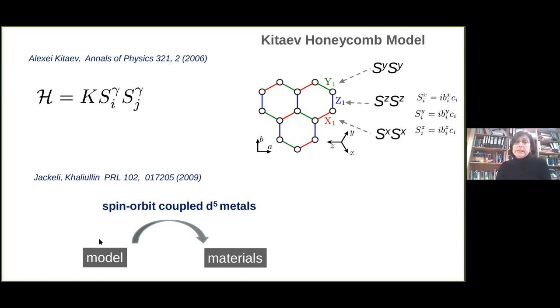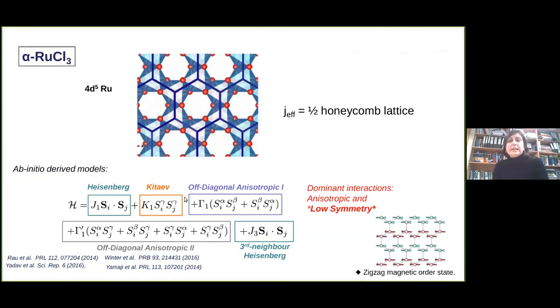The second important work in this field is the work of George Jackeli and Giniyat Khaliullin, where they basically developed a recipe on how to have this type of model realized in a real material. And from there, I think that there was an explosion of work done on studies of materials where one could find this type of physics predicted for the Kitaev model. So one of the most intensively studied materials, as I was mentioning, is alpha-ruthenium trichloride, which is a system that consists of layers of honeycomb lattice where we have ruthenium basically in the corners of the honeycomb, and it fulfills in principle all the conditions that we need for a Kitaev interaction.